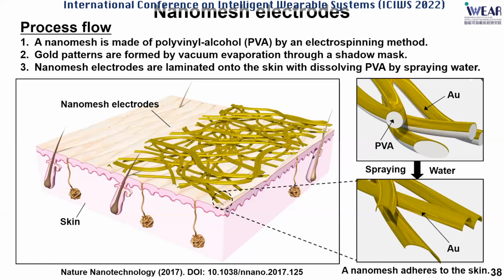Okay, so this slide shows you the fabrication of a nanomesh device. The polyvinyl alcohol is used to form the nanomesh by the electrospinning method, and the gold patterns are formed by vacuum evaporation through a shadow mask. This device was put on the surface of the skin, and water is applied by spraying, and the PVA is dissolved in water and washed away completely. And finally, the porous gold film remains. In other words, PVA is used as a sacrificial layer, and only thin film gold remains on the surface of the skin.